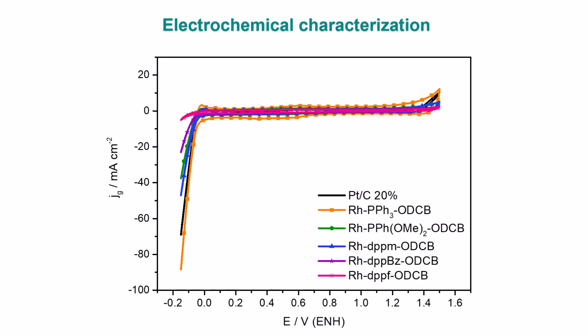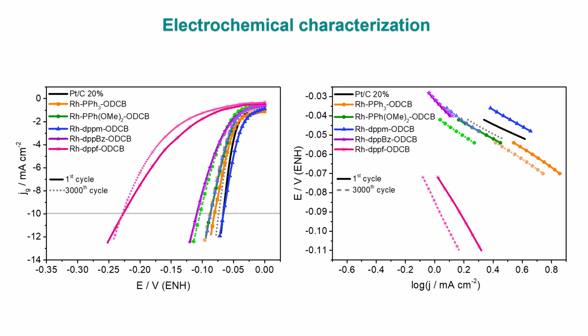The electrocatalytic activity toward the hydrogen evolution reaction was evaluated in 0.5 molar sulfuric acid using a rotating disc electrode. All synthesized rhodium clusters were active for hydrogen evolution, although clear differences in catalytic performance were observed depending on the coordinated phosphine ligand. Catalyst stability was evaluated by comparing the electrochemical response before and after 3,000 potential cycles. Most catalysts maintain their activity after prolonged cycling, demonstrating good electrochemical stability under acidic operating conditions.